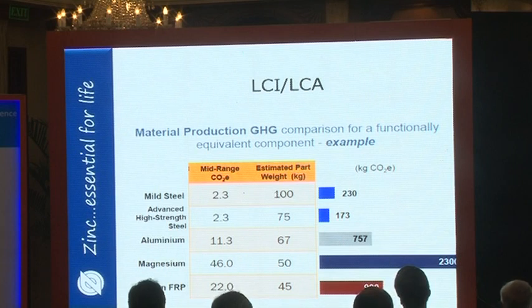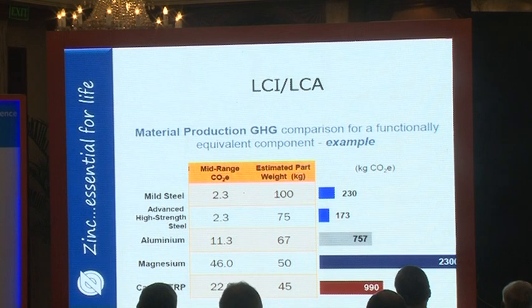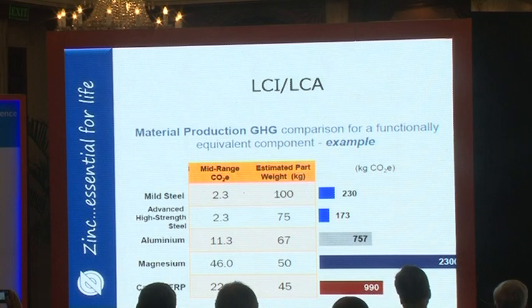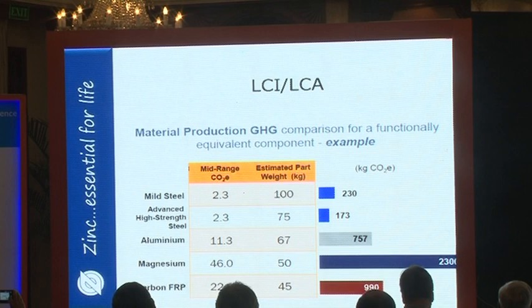And we have to be very careful about this when we look at the substitution of lighter weight materials. We show the mid-range carbon dioxide emission, and you can see that the production of the material itself is highly favorable for the steels. As you get into primary aluminum, and it is only primary aluminum that we'll be making automobiles out of in the aluminum-based cars, and magnesium and carbon fiber reinforced plastics, there are even higher greenhouse gas loads. And we see here the part weight that is made from them.